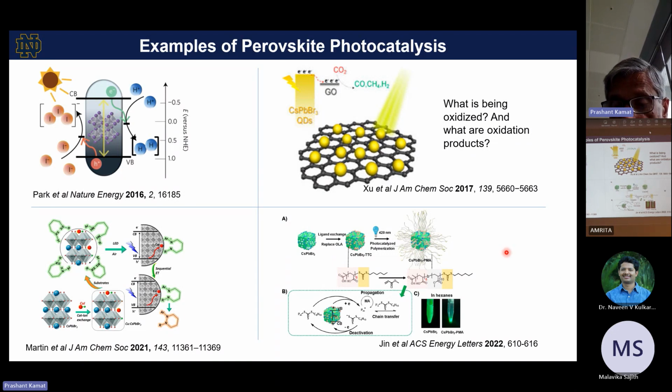And this is one that our colleague at Notre Dame did, trying to polymerize by a photocatalytic method. They substituted these ligands with these methacrylate monomers, and then you shine light at 420 nanometers, and that led to this photopolymerization. And then this one is stable even in polar media. So I'm coming back to that one a little later.